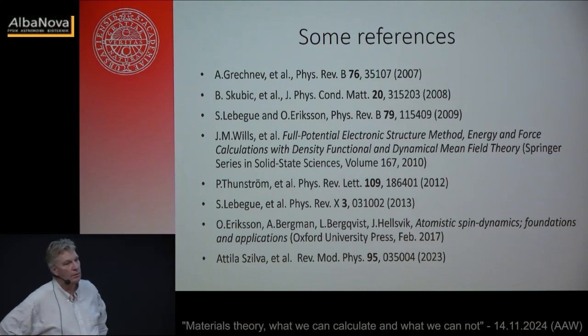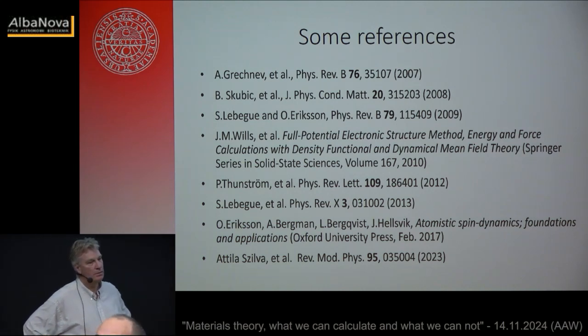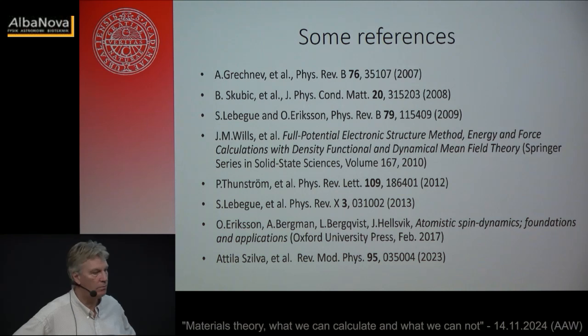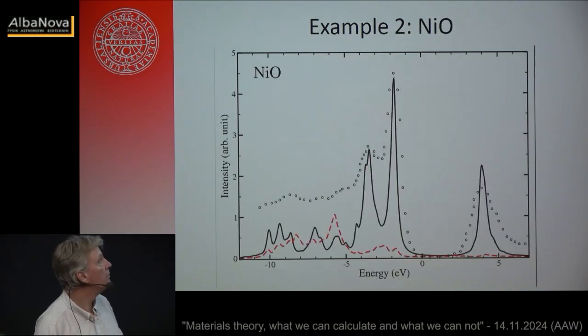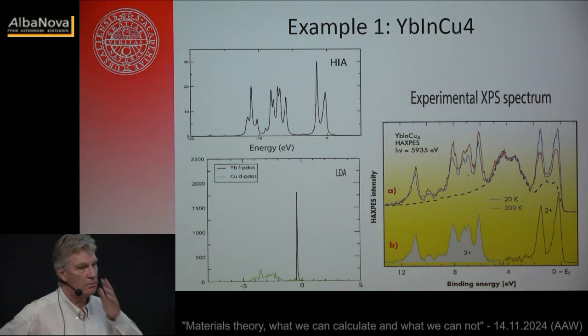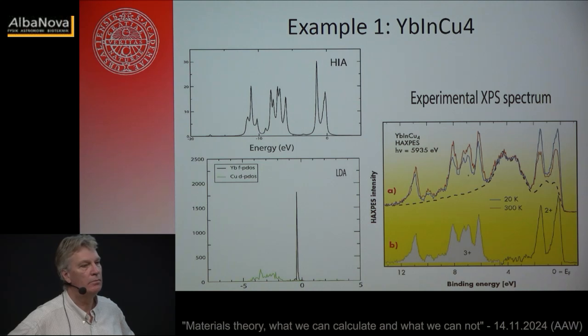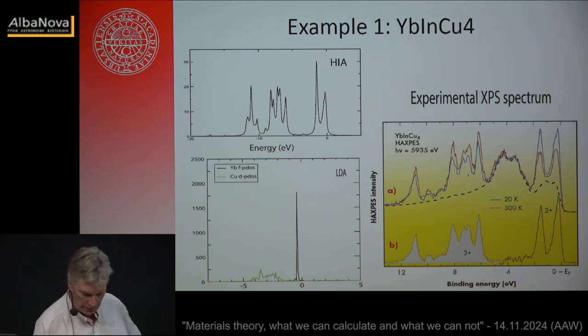So you compare the DFT density of states, and as you pointed out, there's no reason that this should look like the spectra. Then you compare it to DMFT, where you have some sort of frequency dependence, and it makes more sense to actually calculate excitations. Yes. But wouldn't the fair comparison be to do time-dependent DFT and compare that to the experimental data? And is there a sort of systematic?